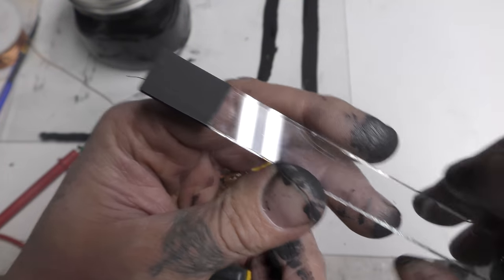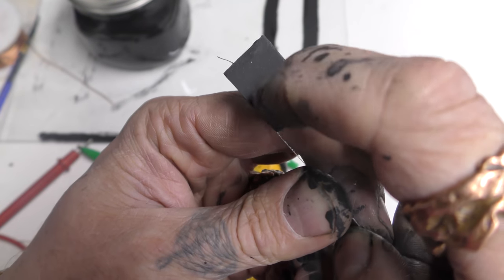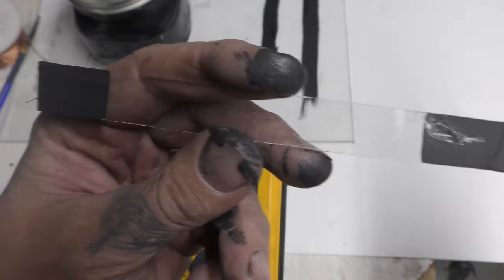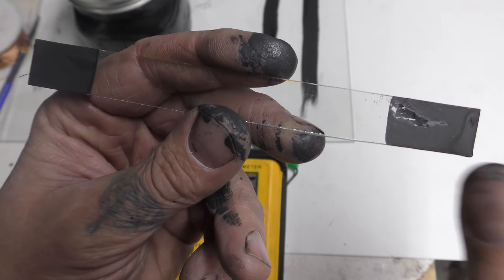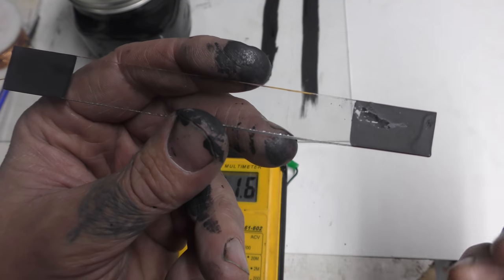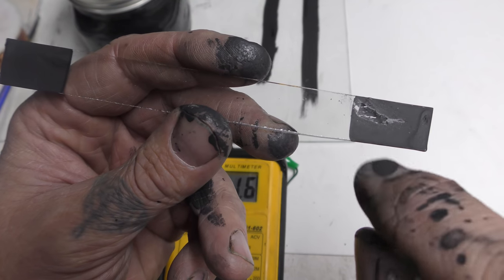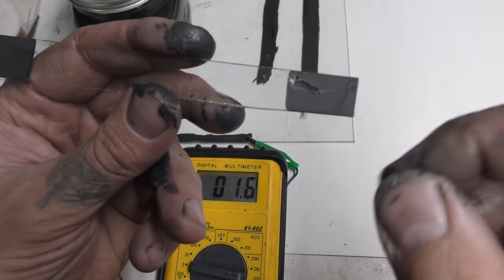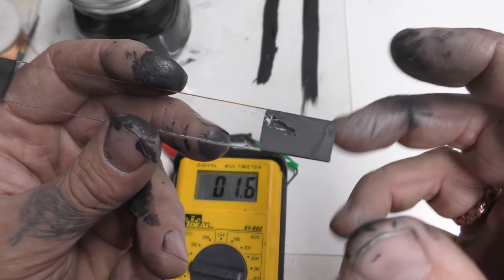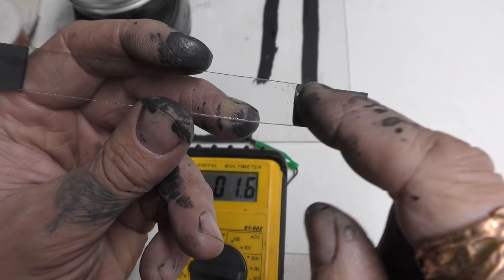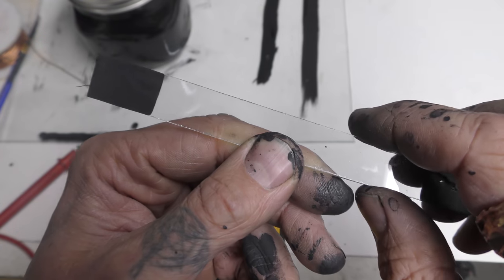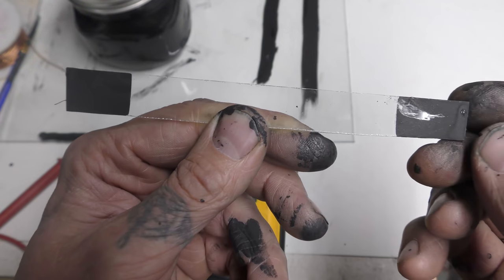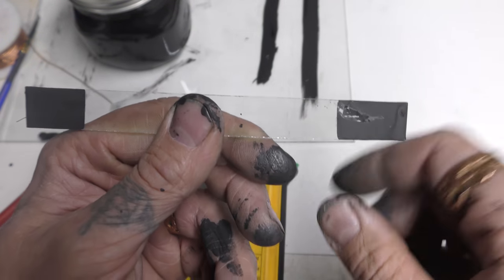So, I can scrape it off of my fingernail. Okay. Where this one over here has a higher ratio and I can't scrape that off. Now, why would you care about that? Because of detail. Okay. So, for leaves, bugs, insects, stuff like that, you don't need a whole lot of adhesion or toughness. Because you're going to have a conductive surface on it growing. So, this would allow lots of detail to show up. Where this one wouldn't allow a whole lot of detail to show up.